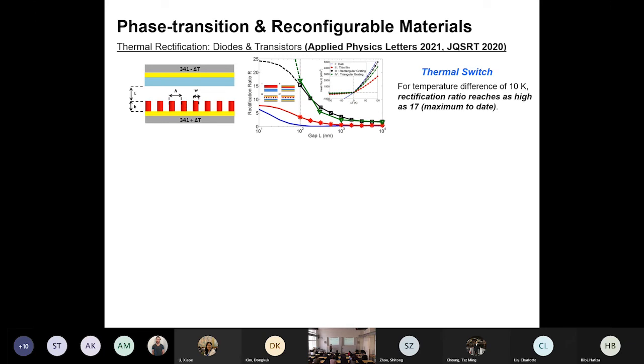Without the use of phase change material, you can imagine this ratio should be 1. So the forward should equal backward. But with the use of phase change material, this ratio is greater than 1. So far we're able to achieve as high as 17. But actually in the paper we published last year in 2021, in APL, we already increased this ratio from 17 up to 146. So that is the highest ratio we obtained so far.